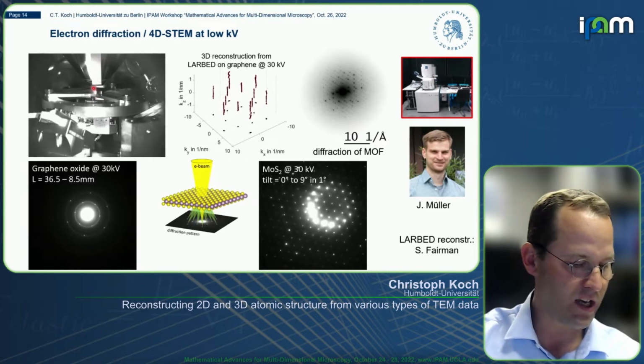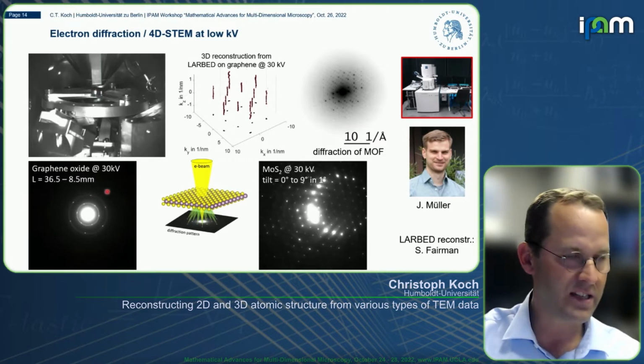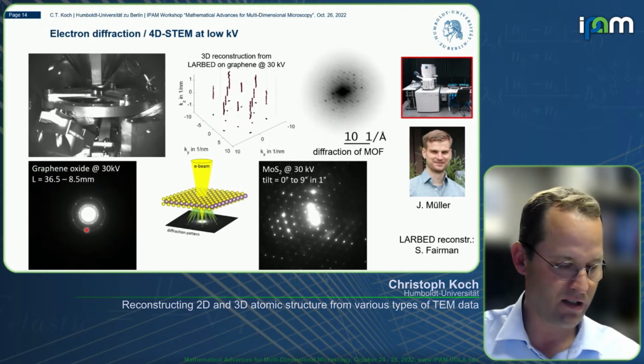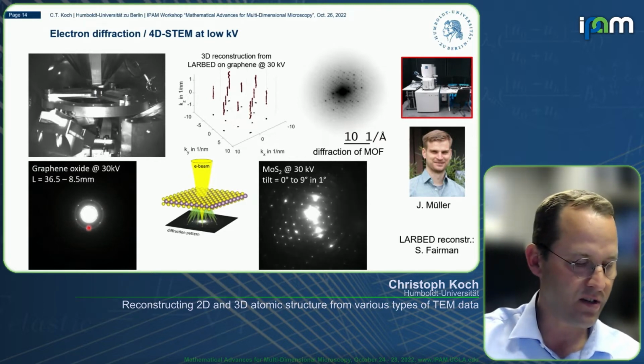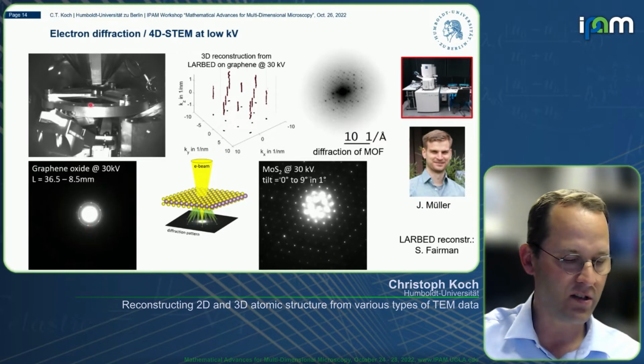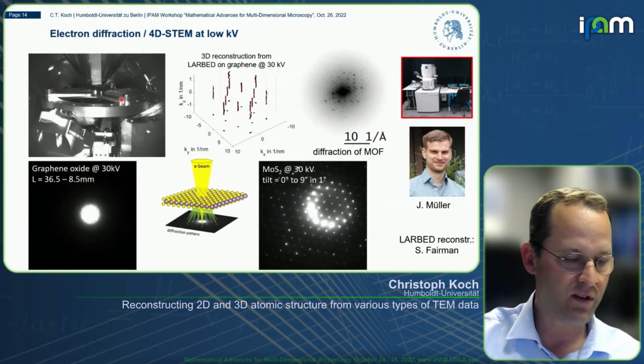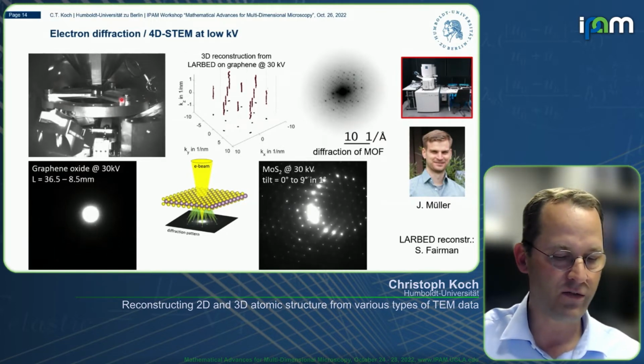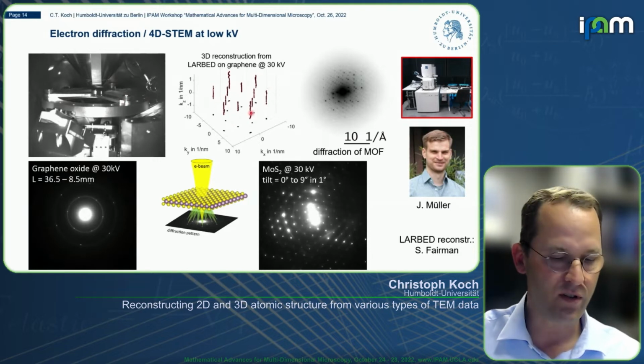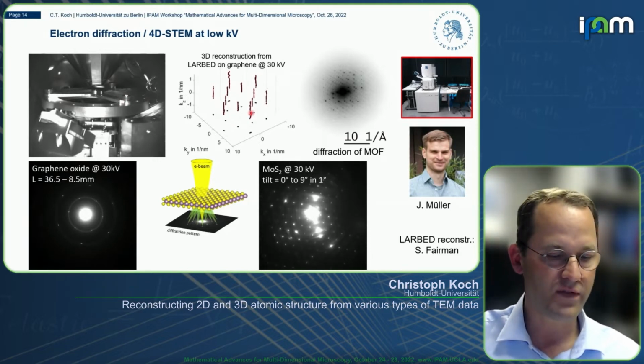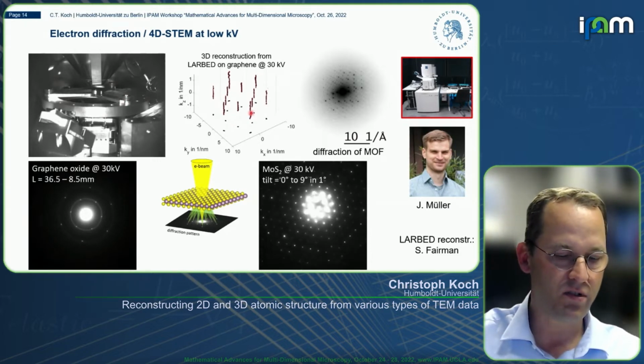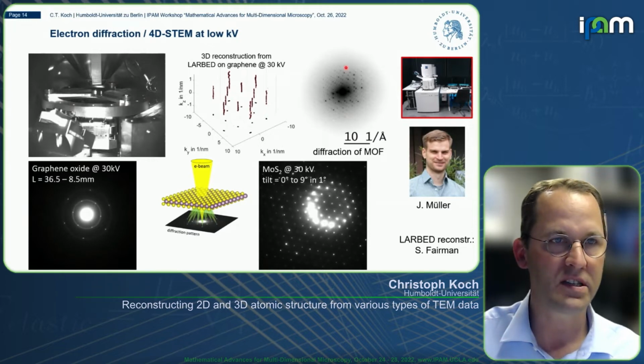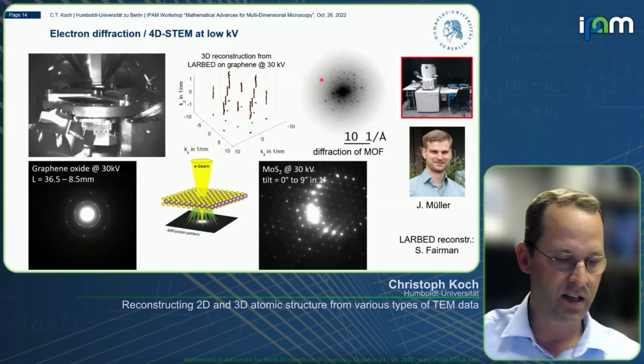And you can see how when you change the camera length, the size of the diffraction pattern actually physically changes. You can also tilt, because this is now a 6-axis goniometer. You can tilt the sample and recover, for example, 3-dimensional diffraction information. Because you have such low voltage and you can really control your dose very nicely, you can now also record diffraction patterns from very beam-sensitive materials like these MOFs.